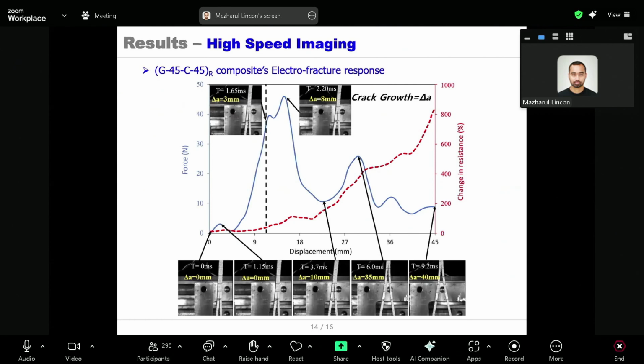Now after that, applied force decreases, and also when the second load pulse is applied, again the force actually increases, and the change in resistance also starts increasing. After that, again some small peak is observed because of the third and fourth loading, and this is the time when the whole specimen actually breaks, and 45 millimeter crack growth happens with complete breakage, and we got the peak piezoresistance change around 800%.